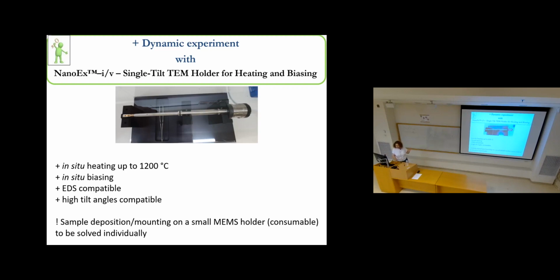So this dynamic experiment was not available with our old TEM, and it was not available with any of our TEM because we didn't have heating holders. So the only dynamic experiments we succeeded to do in the past with F20 was acquisition of the coalescence of silver nanoparticles on grid, using not the main detector, the Gatan slow scan camera, but the TV camera and the home DVD recorder. So now we can acquire films, movies about, for example, transformation of the crystal structure under heating and under cooling. So this is a cooling from the target temperature down to room temperature, but controllable. Okay, this holder allows controllable heating and cooling and biasing.